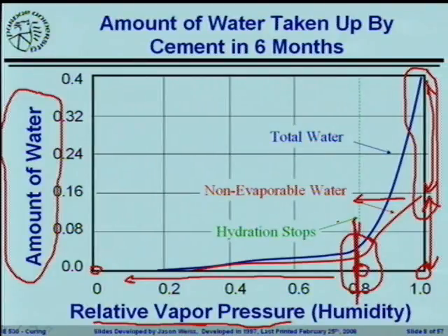So temperature changes are going to be the most dramatic at the surface. Humidity changes are going to be most dramatic at the surface. So the big problem here is you may get a surface that comes to 60 or 70% relative humidity fairly quickly and stops reacting. The core of the concrete continues to react, so when you measure a cylinder, you don't see a big difference in the overall strength because the majority of the cylinder is the core of the cylinder. But if you start to look at ions going into that concrete, salt getting sucked into the system, the diffusion into the system, that surface concrete, conveniently called cover concrete by a lot of people in the business, is going to be much more porous than the core part of the concrete and allow many more things to come into the overall system.